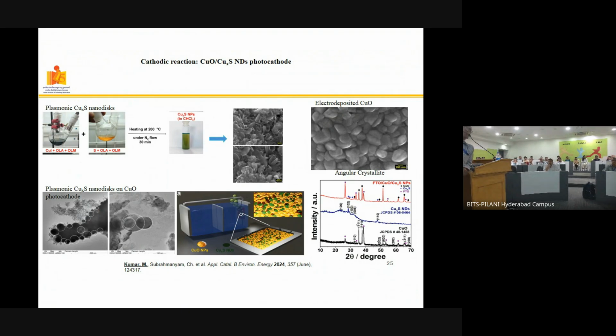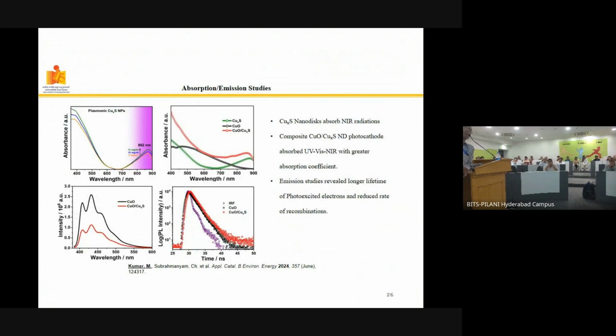And if you try to just heat it and reduce it, because you have some sulfur which is present there, it's reducing it, converting to sulfide. So this one we try to use in combination with the copper oxide and copper sulfide. So that combination, you can actually see the beautiful dispersion happening in this case. So this is where you can try to play with this combination for this p-type material.